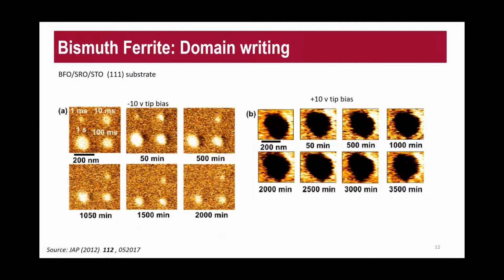And we can also use PFM for domain writing. What is exactly shown in this paper is the relaxation evolution of BFO domains created by pulse voltages, because PFM has a range of electric field from positive and negative 10 volts, and by applying these pulse voltages to it, you will see two distinct different contrasts.